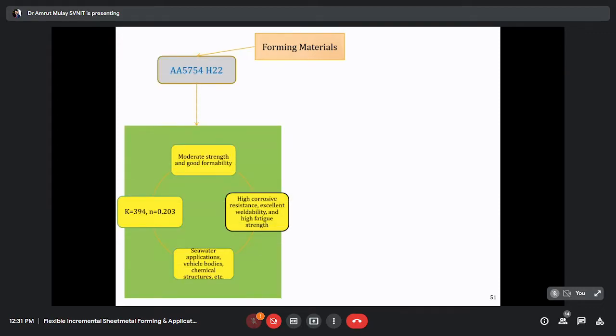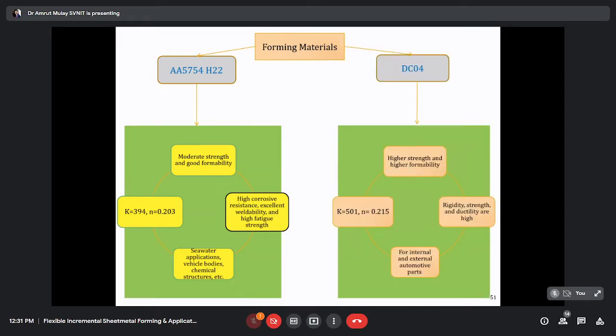This is the study performed at Warsaw University of Technology, where they investigated two materials. One is in the aluminum series and one is DC04 series. Here you can see that K stands for strength coefficient, and N is the strain hardening exponent. You can see there is a different strength and therefore different K values and N values. I would like to tell you that a higher value of N, the strain hardening exponent, gives you more formability, and these values are obtained using tensile testing of a material, using a uniaxial tensile testing machine, right?